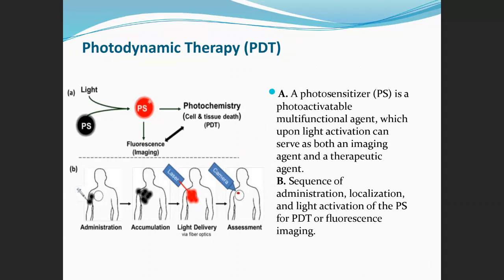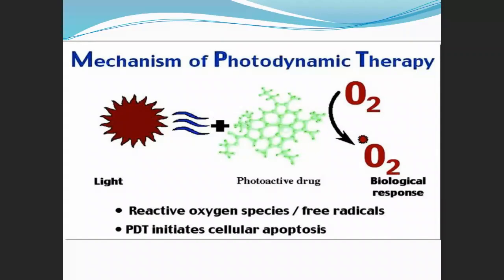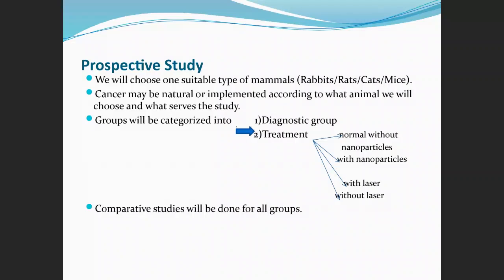laser of specific wavelengths, around 800 nanometers, to be absorbed by the gold nanoparticles, and it generates heat and free radicals of oxygen, which eliminate the tumor. Of course, heat and free radicals of oxygen are aggressive to all the tissue.